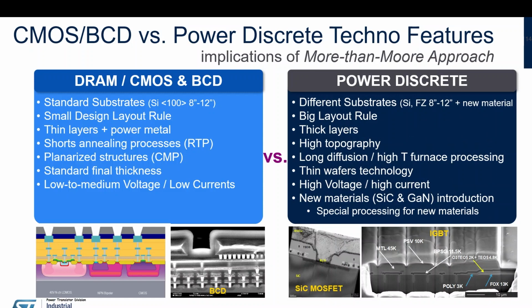If you move to power devices, you have different things to take into account. First of all, the use of epitaxy, much more than in the other case. You typically use thicker layers. You have high topography in the structure. You have long diffusion times and high temperature processes. You have to use and manage thin wafer technology in manufacturing, bringing the wafer down to, say, 40, 50 micron, but still having some of your front-end process performed after the thinning, which is not common in CMOS. You have to withstand high voltage, high electric field, and introduce, as I said before, new materials progressively.